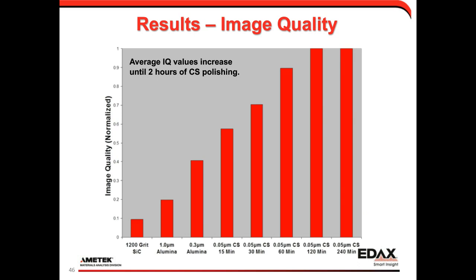And if we then show, instead of showing the maps, we show this on a chart, we see normalized image quality here, that as we continually polish the surface, we see an improvement in image quality value up until we get about 2 hours of colloidal silica polishing. Then it starts plateauing. Going from 2 hours to 4 hours didn't really make much difference in image quality. It's important to know with image quality, it's a function of a lot of things, and we tried to keep as many as we could constant. It's a function of camera settings, of beam current, of orientation, so we sample a lot of grains. But by using an average, we can clearly see the trend that's occurring as we prepare the sample step by step.